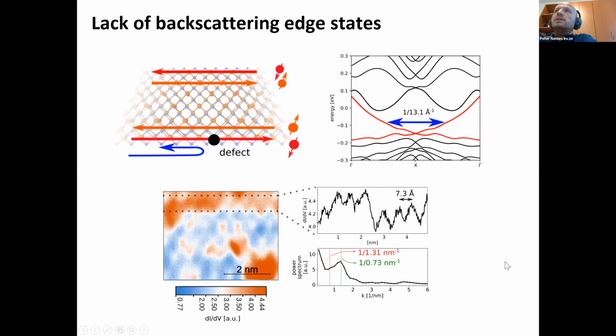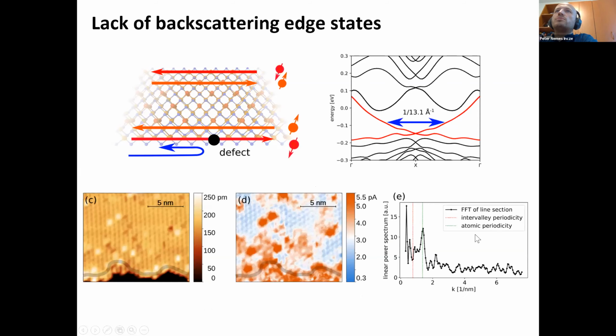So this is an indication that indeed, backscattering is suppressed in these edge channels, as it should be for a topologically protected edge state. This even works if you take a very disordered edge. So this is just a straight edge that I've shown you, but here you can see this very winding edge, which has a lot of adsorbates and defects, and it's not crystallographically perfect. But still, you would expect to see an increased density of states, which we do.